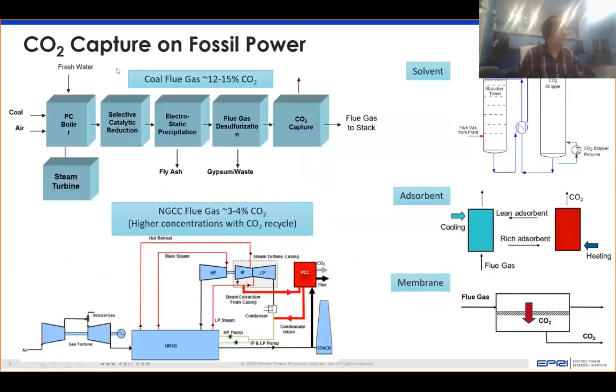And what that looks like, at least in the case of a post-combustion process, is just like you have a boiler followed by SCR and electrostatic precipitators and now FGDs. The thought is to put in essentially an additional environmental control unit here, which is CO2 capture. In the case of coal, CO2 is about 12 to 15%. When you have a natural gas combined cycle, it's 3 to 4% or so. In some cases, it's advantageous to recycle the CO2 back to increase its concentration so that capturing CO2 is easier.